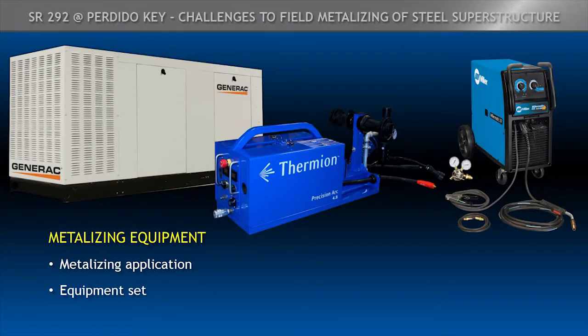This is a picture of some of the newer equipment, not that we used all of this, but you can see that you have to have a generator, a welding machine type, and then the wire feed. And all of these things had to go out. The generator was on the barge. The wire feed goes into the containment where you can keep it close to the surface, within about 25 feet. And then the welding machine, they actually set up platforms up top so they would be close to the wire feed. And for all these things, the manufacturer came out and made sure it worked right to give us a specified product.